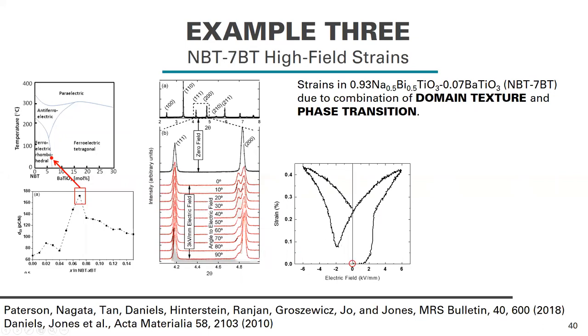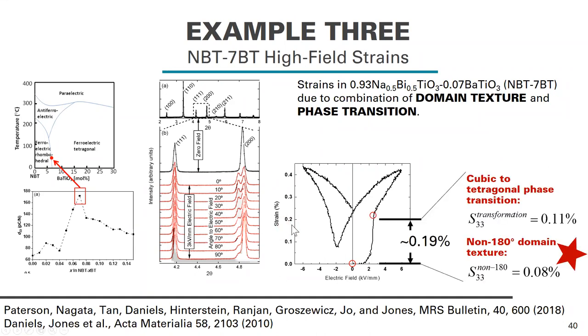And one question is, as we trace the hysteresis loop of this particular material, how much of this strain is due to the phase transformation or phase transition, and how much of it is due to the alignment of domains in the tetragonal phase? And again, without going into too much detail, which would go beyond one slide, I show you this calculation at the bottom, which is calculated using the methods described on the prior slides.